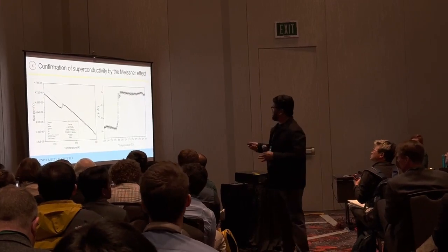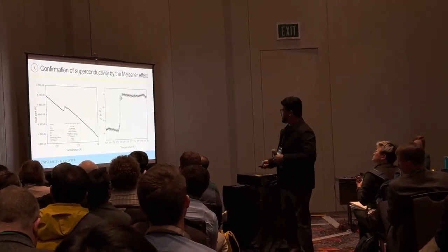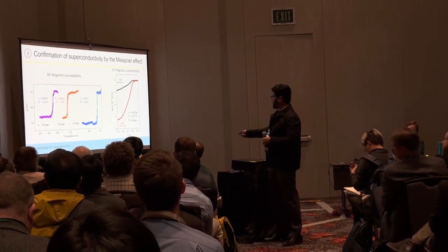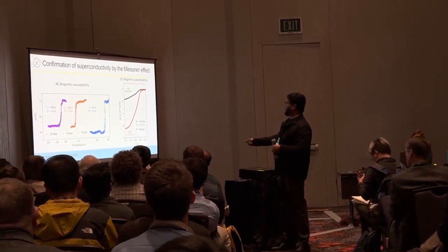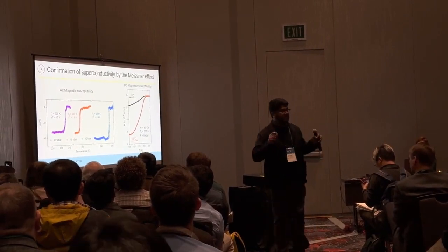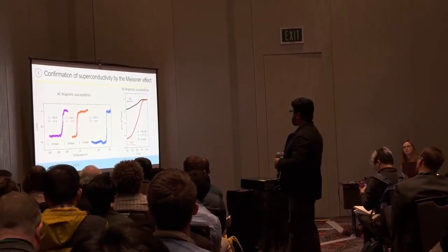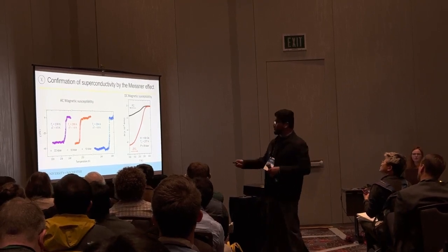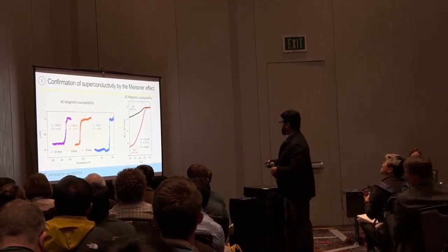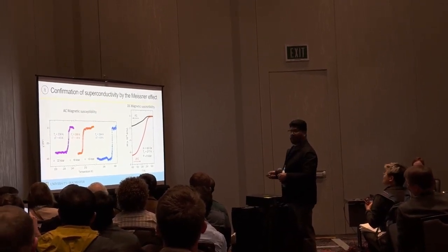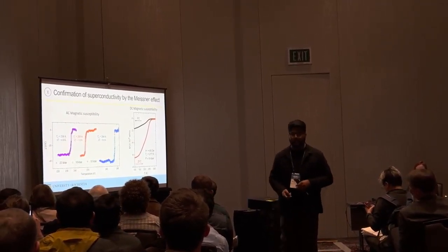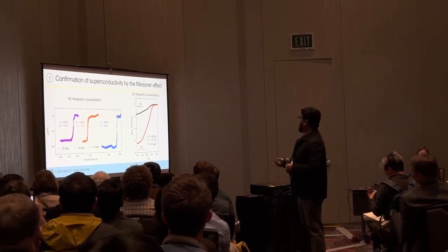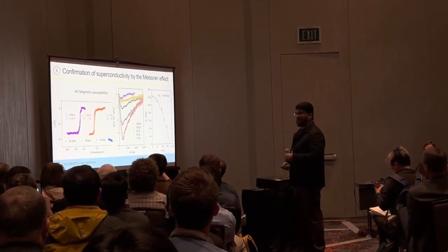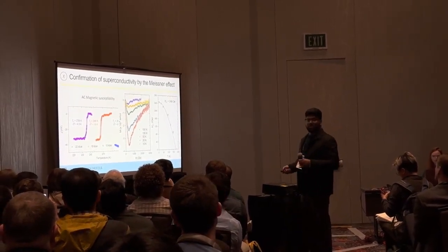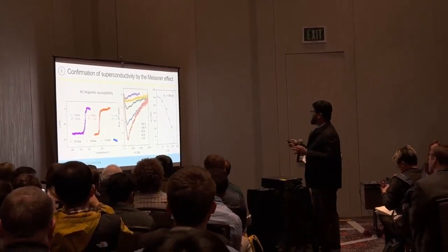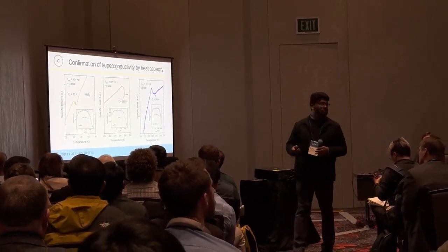So what we have done is the AC susceptibility for different pressures. These are 3 different pressures that we are showing you, 10, 16, 22, with the TC as high as 294 Kelvin. So this is the AC magnetic susceptibility. And we have done the DC magnetic susceptibility as well, the true representation of the Meissner effect. You see the shielding, zero field cooling and field cooling, showing the diamagnetic response from the DC measurement as well. And then thirdly, we have done the magnetization curve to see this diamagnetic response. So that's the second technique that we use to prove the superconducting transition.